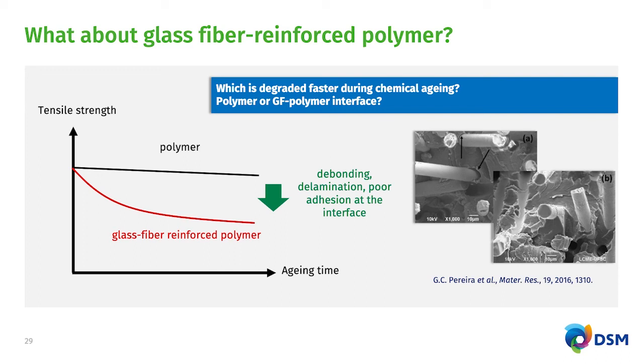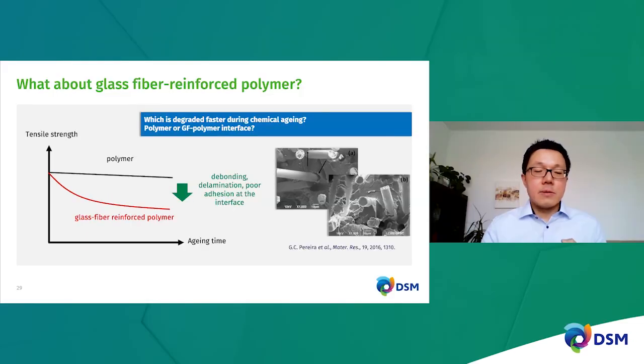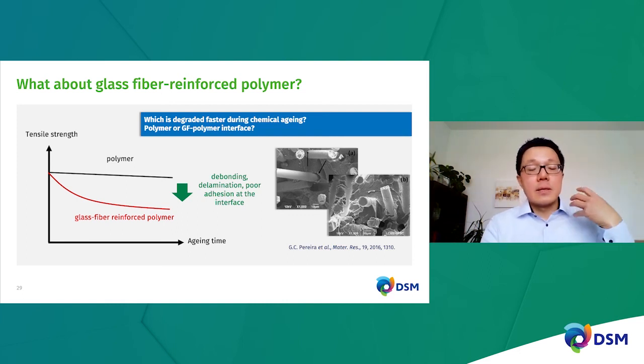Now, if you imagine that you are, for example, using PPS, a super high chemical resistant grade, usually what happens is that you don't degrade the polymer, but you degrade the polymer glass fiber interface. So if you overlap, let's say, the tensile strength retention of such a polymer versus the glass fiber reinforced version of those, so we're talking about unfilled PPS versus glass filled PPS, usually for unfilled PPS, you don't have a lot of reduction in tensile strength, but as soon as you introduce glass fiber where the interface is not optimized, you see that reduction.